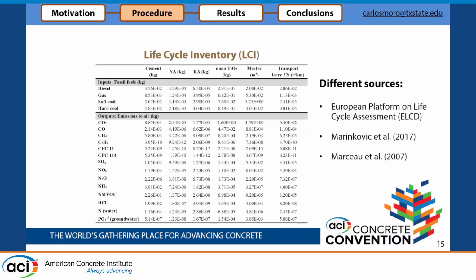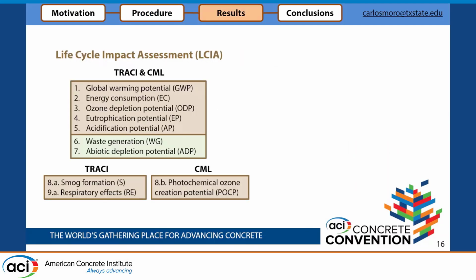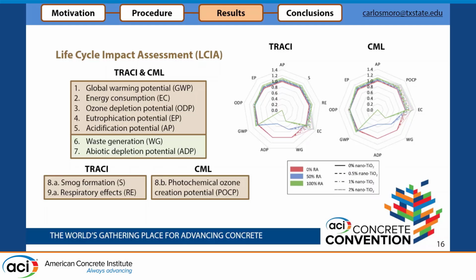Okay? For the life cycle inventory, we use different sources like the European platform, but also other previous research. And for the categories used, we use the TRACI analysis, well, TRACI and also the European one that is called CML. And not only we use the categories included in those, but also included waste generation and abiotic depletion, because whenever we are dealing with a recycled material, we need to use those in order to have a fair analysis. So our results show very similar results, regardless of the methodology used. That means that the American TRACI and the European CML show more or less the same results.